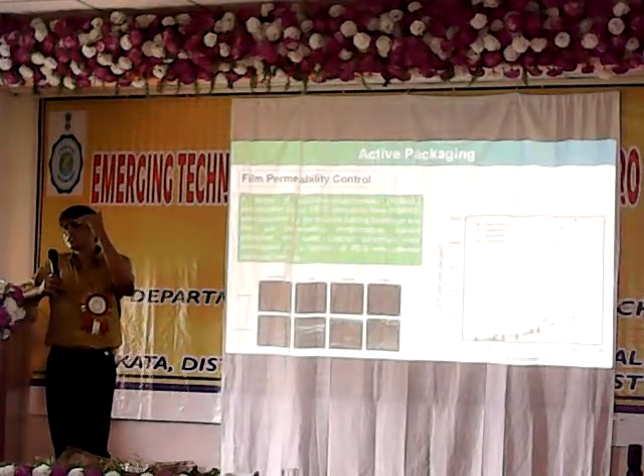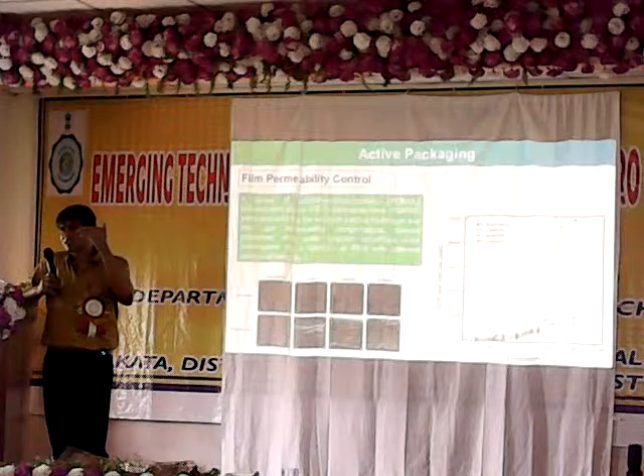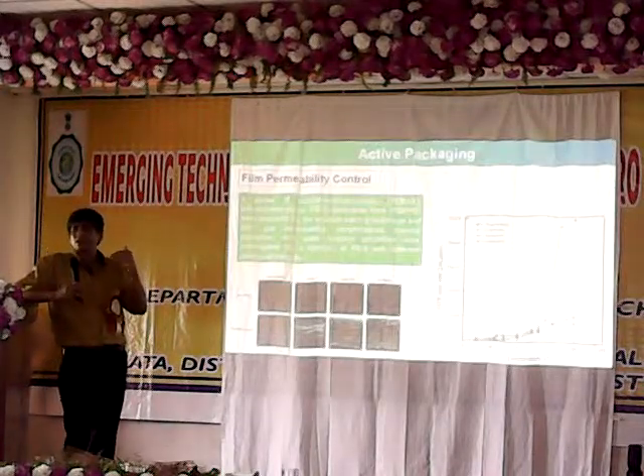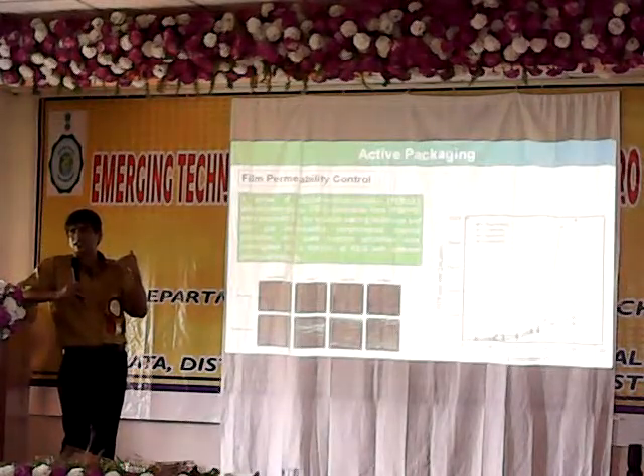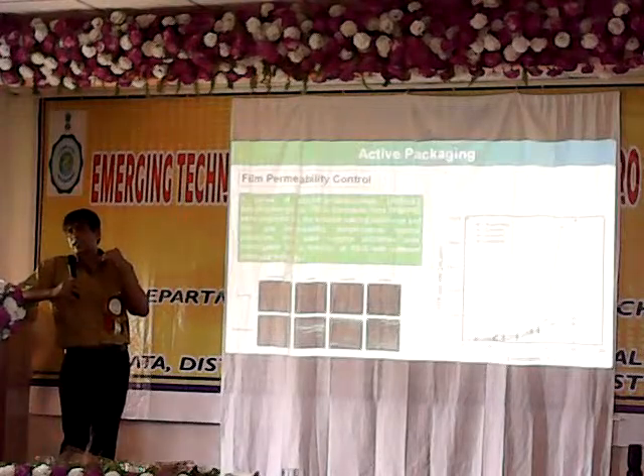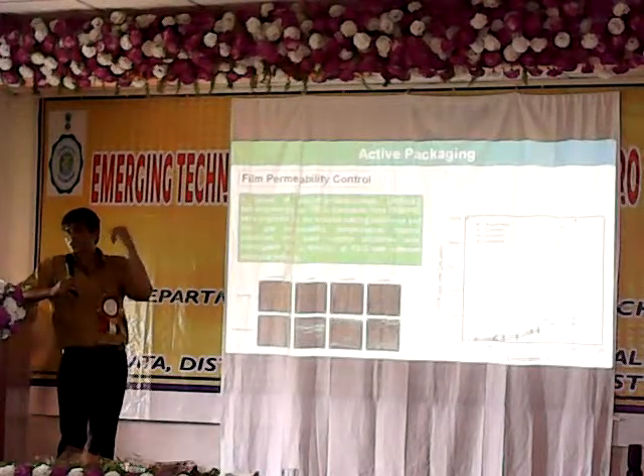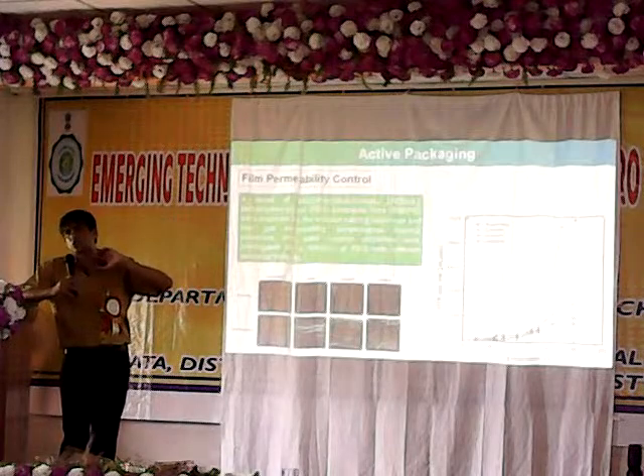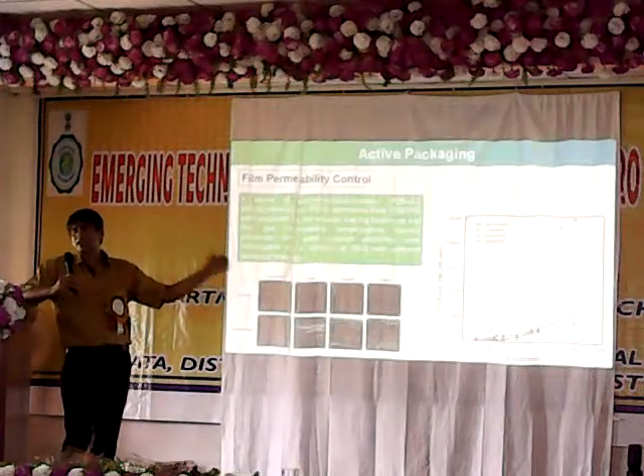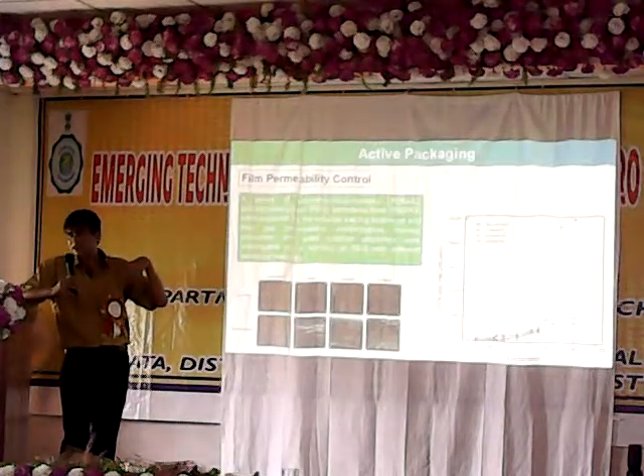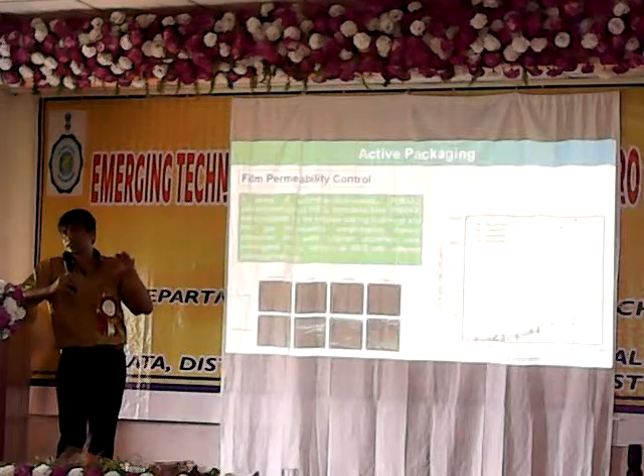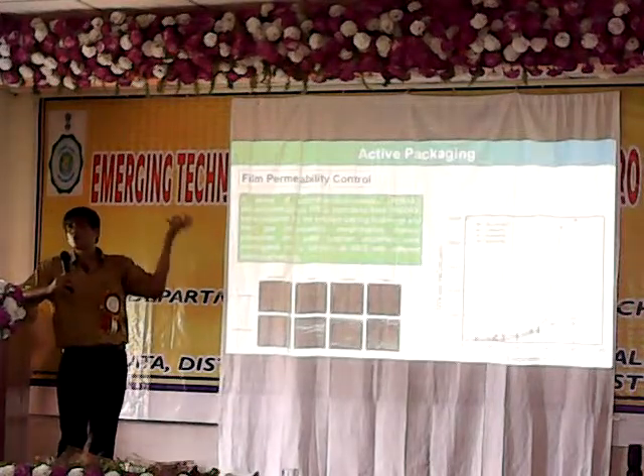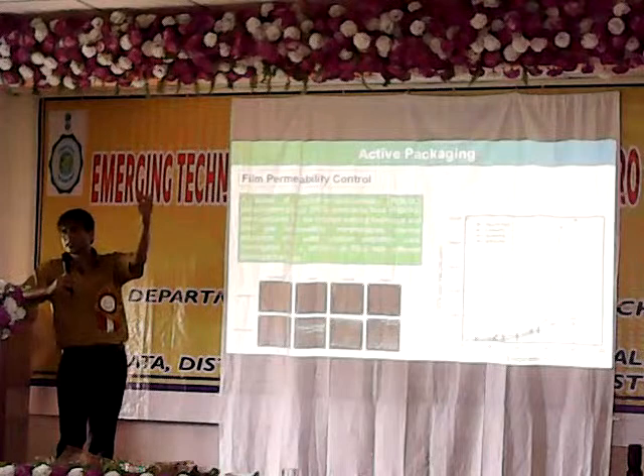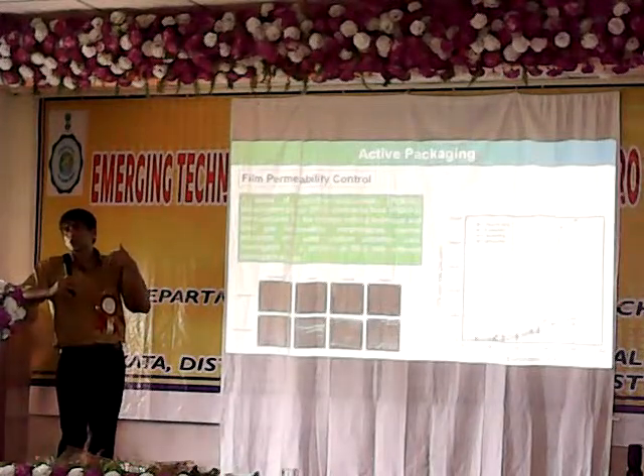But at 40 degrees centigrade, it is 4 or 5 times more than at 10 degrees centigrade. So as the respiration rate increases, there is a further requirement for carbon dioxide to release out of the packet and oxygen to come into the packet to sustain that respiration rate. So we need a more porous film at 40 degrees centigrade than at 10 degrees centigrade. Now what do we do?